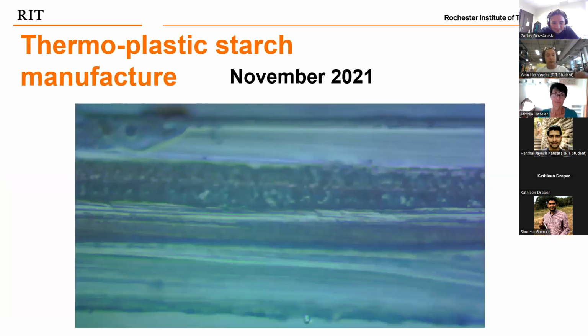And then we were able to use it in a blown film and make multi-layered films. However, we got a 5-layer and not a 3-layer, which was what we wanted, but it was a breakthrough in the sense that we were able to do this multi-layer film. We were able to see for the first time that starch layer there in the middle.